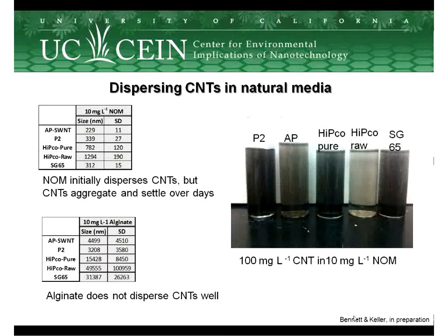These sizes, you have to sort of think what you're really seeing, because a particular carbon tube may not have this particular dimension. The instrument is trying to average a very thin diameter with a very long fiber, and so this number is really reflective of what the light may interact with that particular tube. But smaller dimensions, we really should just call it dimensions, are a better indication of better dispersion than these very large ones. So clearly, these are not successful so far.